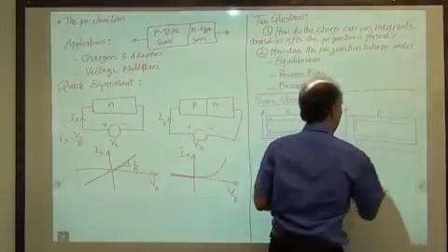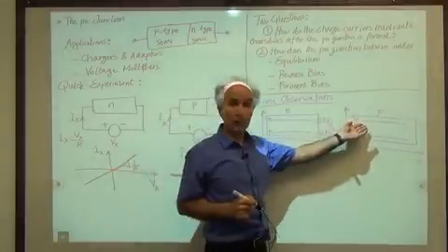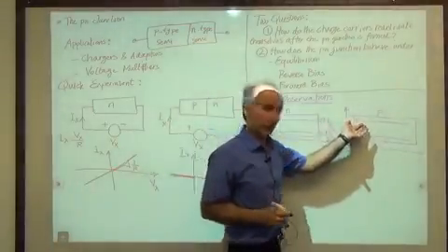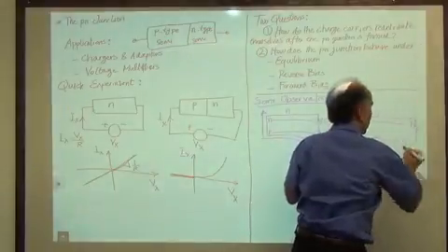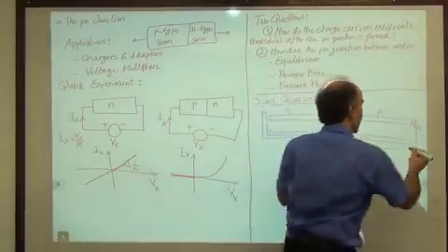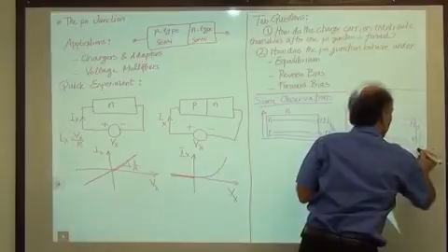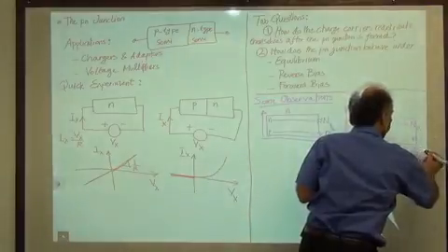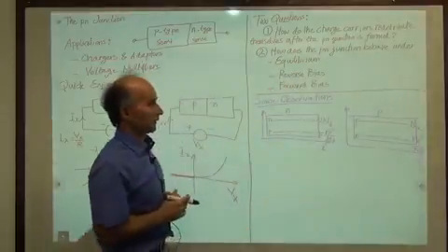So that's N. And we saw that the number of holes per cubic centimeter is given by the concentration of acceptor atoms, N_A, whereas the number of electrons is given by n_i squared over N_A. I hope you can read this on the screen.